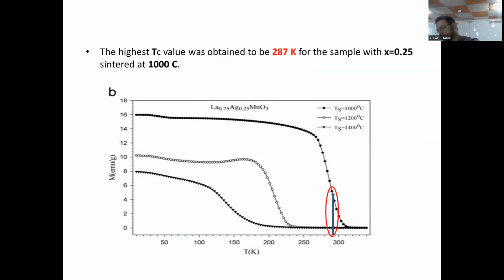Here now we are talking about the Curie temperature. When the Curie temperature is near or around room temperature, that means our work is better. Here at the 1000 sintering temperature, the Curie temperature is nearest to room temperature, approximately 287, but the others are far away from room temperature. We can say the Curie temperature here is less than 200, and here is less than 150 Kelvin. That means it's far away from room temperature. That means the better situation is at 1000 Celsius.